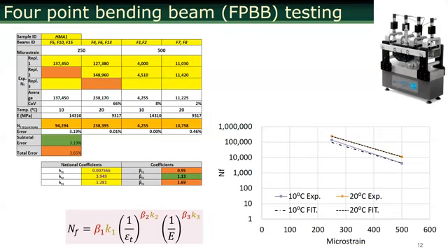This is a fatigue test. So for a fatigue test, you don't need to run at very high temperatures or very low temperatures, because fatigue happens at intermediate temperatures. So anywhere between 10 degrees to, I would say, 30 degrees Celsius. And how did I decide 10 and 20? Based on gut feeling. Really, there's no standard for that. We're just trying to come up with a relationship. Maybe if someone's in Florida, they're going to test at higher temperature. Yes, like 20 and 25, or maybe it's different at higher temperatures.